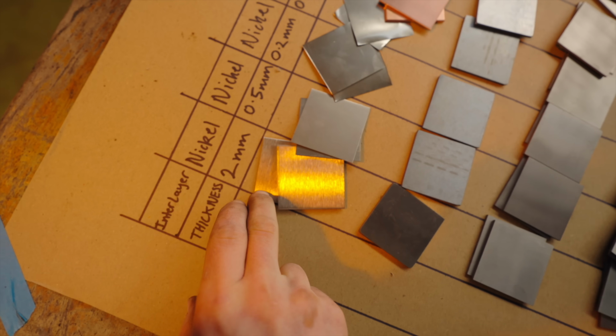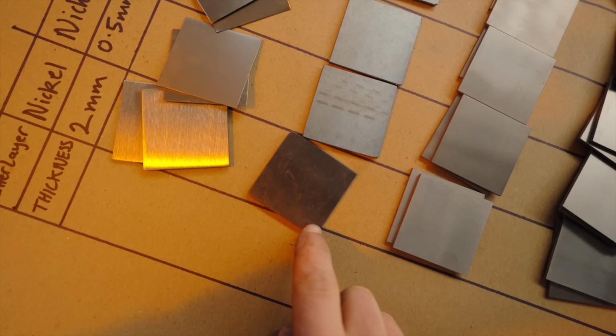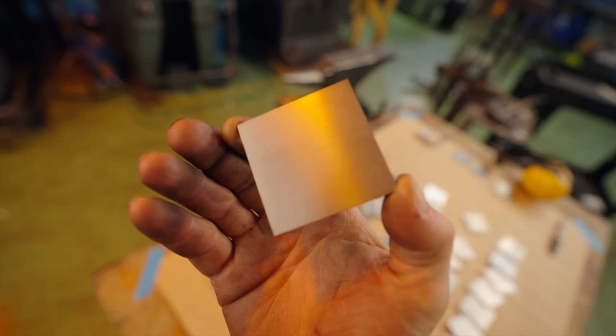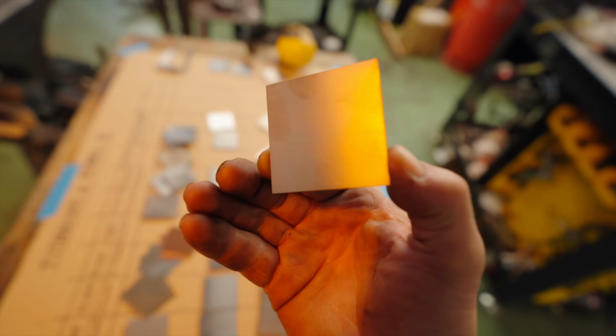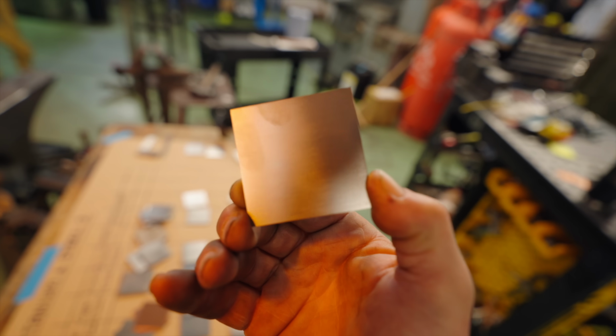Righto, we've got most of our material prepped. As you can see in this example, 2mm nickel interlayer. The steel is going to be in the middle. This is our grade 2 or commercially pure titanium. This is grade 5, so it has some aluminium and vanadium in the alloy.